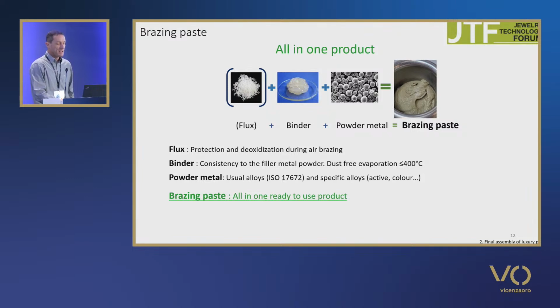What is brazing paste? A brazing paste is a mix of a flux, a binder, and a powder metal. The flux has a first shielding effect on the components, and when it completely melts, it creates a deoxidation in order to protect the filler metal. The binder allows the powder to be packaged and dispensed. So brazing paste is an all-in-one, ready-to-use product.